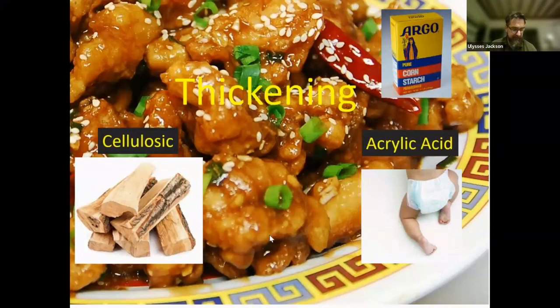And then finally, with water-based paint, what's interesting is they all start as a low viscosity system, and then we use chemical thickeners to thicken them up. So the different classes are generally a cellulosic thickener. So you can think of dissolved cellulose like wood or cotton or something along those lines. They dissolve it really fine, and then add functional groups onto that allow it to swell in an alkaline environment. And so this is very similar to when you're making Chinese food and you have cornstarch and water and you mix it in with your food and you heat it, or making gravy. And then that will increase in viscosity when the heat activates it. The cellulosic thickeners kind of are similar, but they do it when a high pH activates it.